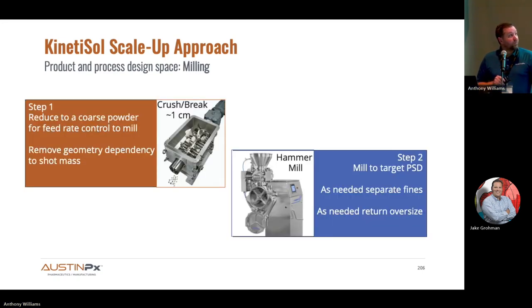So then we get the material out of the machine to provide a dispersion that's suitable for finished dose manufacturing. We have to mill it. So there's a really practical part that I believe heavily in, that is to do a two-stage milling process. The first reason is because we want to be able to control the feed rate to the mill, and having this big disc makes that kind of hard.